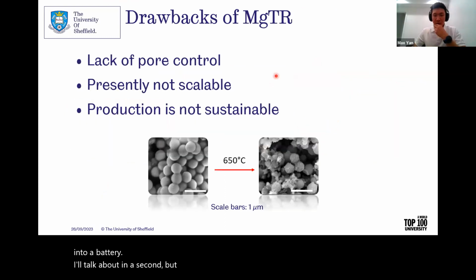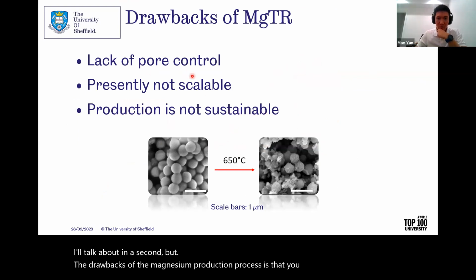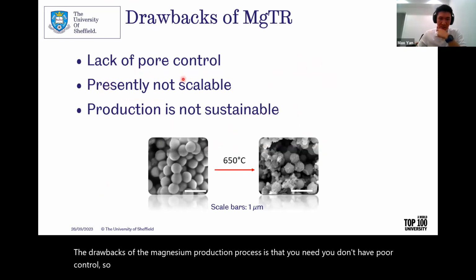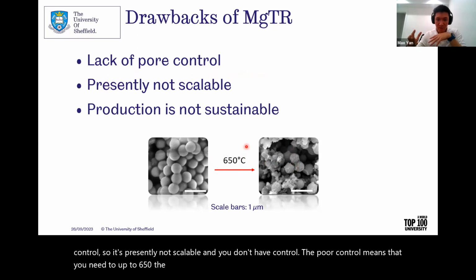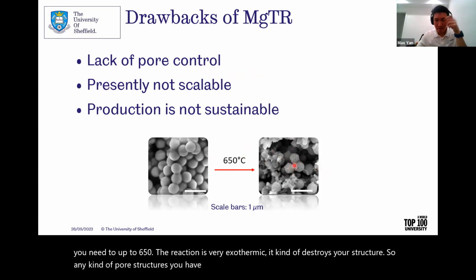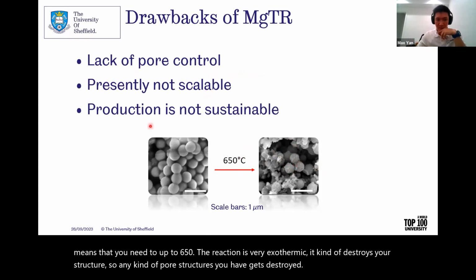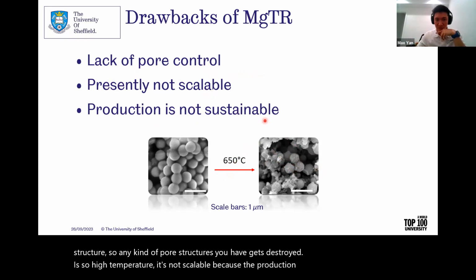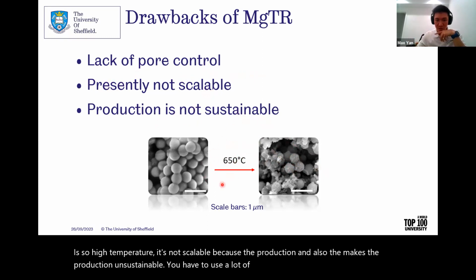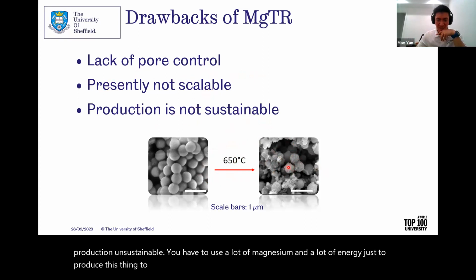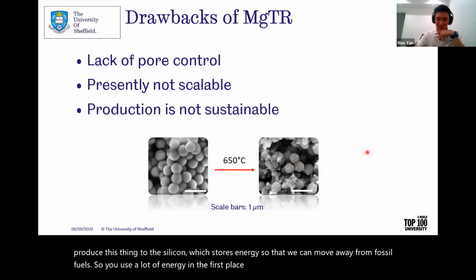But the drawbacks of the magnesiothermic reduction process is that you don't have pore control. So it's presently not scalable and you don't have pore control. The pore control means that you heat it up to 650, the reaction is very exothermic. It kind of destroys your structure. So any kind of pore structures you have gets destroyed. Because it's so high temperature, it's not scalable, and that also makes the production unsustainable. You have to use a lot of magnesium and a lot of energy just to produce this silicon, which stores energy so that we can move away from fossil fuels. So you use a lot of energy in the first place to then save energy, which doesn't really make sense.